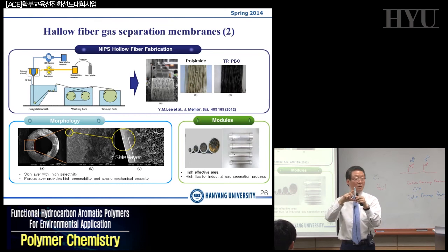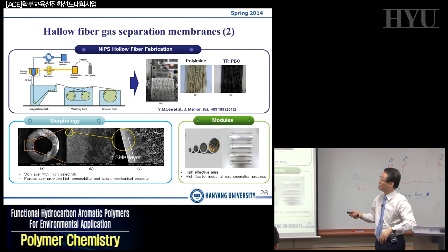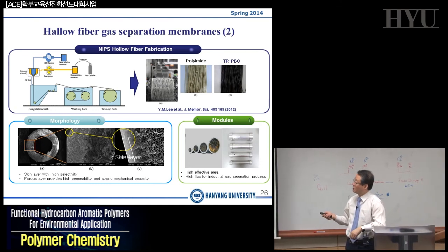So this hole is filled with polymer solution, and if you pressurize it, the polymer solution will go through those small holes. Right? So the polymer solution goes through those holes and into a coagulation bath, which consists of water. Then the water will coagulate or precipitate the polymer solution.